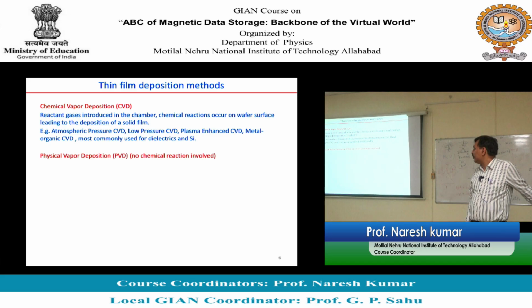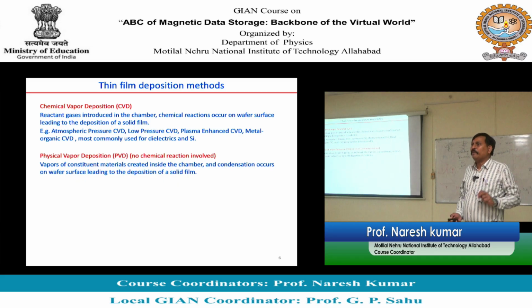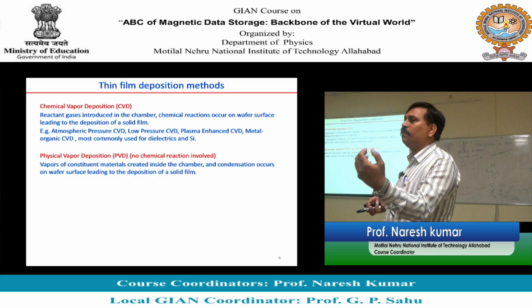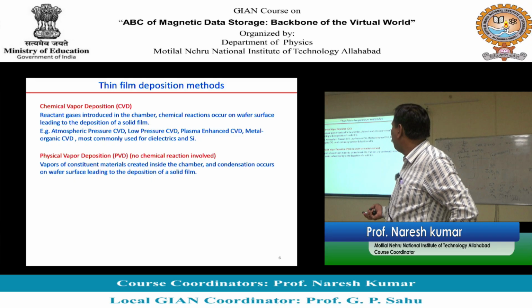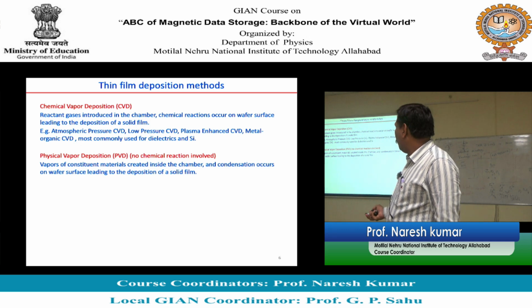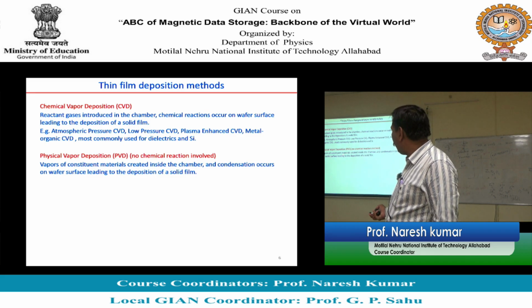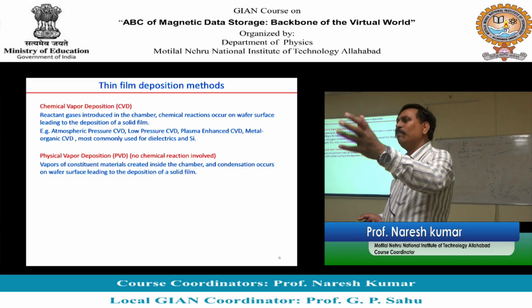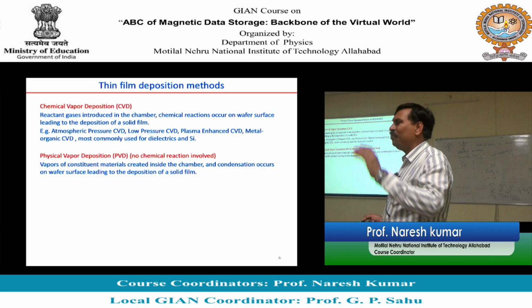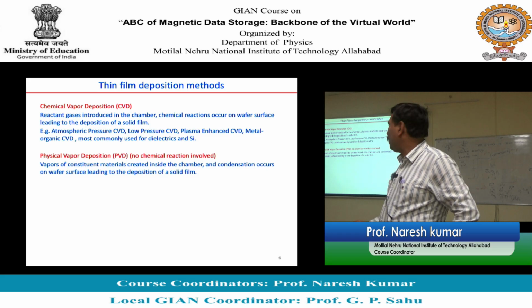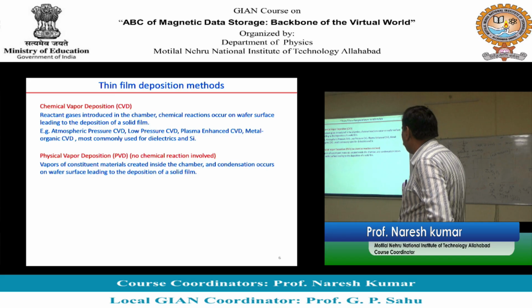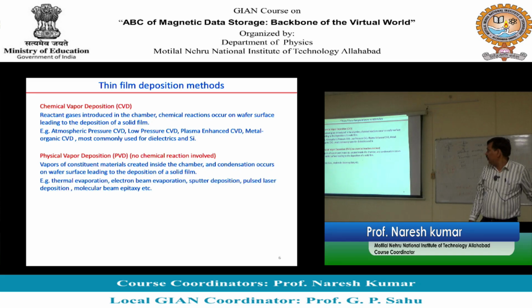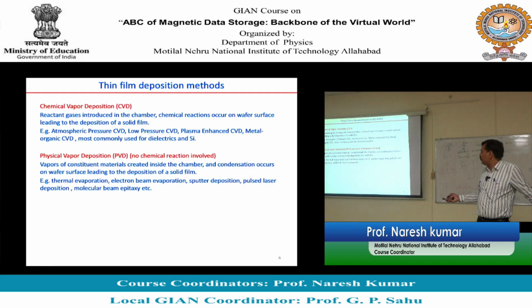We also have one more method. It is physical vapor deposition where no chemical reaction is used. Here you take a target of the material you wish to deposit as thin film, and through some means, plasma or vapors are created. These vapors or plasma are of constituent materials, and they expand in vacuum, making a plasma or plume we call it, and then that plasma goes and sits at the substrate. You have a deposition of film, and this method is your PVD. Here no chemical reaction is involved. There is a list of such methods: thermal evaporation, electron beam evaporation, sputtering, PLD, molecular beam epitaxy.